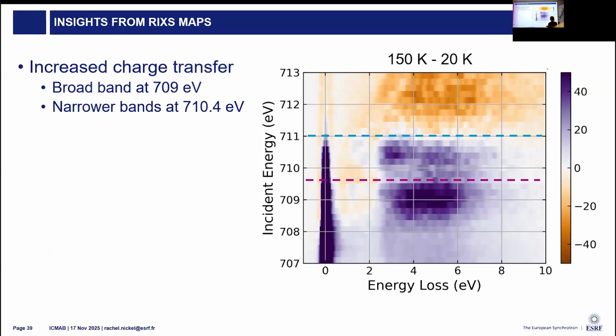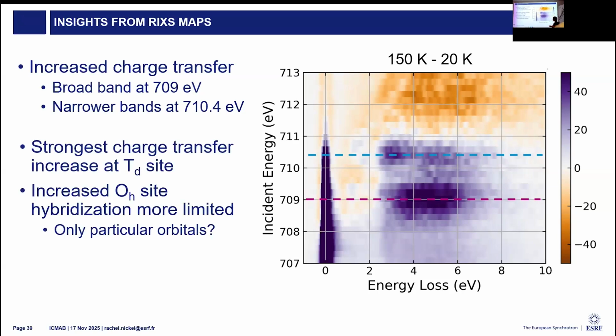So how do we connect it back to the RIXS map? It's an even shift of about 600 meV between where the DDs are resonant and where the charge transfer is most strongly changed. And so we can take these results and attribute it to stronger charge transfer, stronger hybridization of the tetrahedral site, as well as more discrete orbital overlap changes on the octahedral site. It seems that this is only affecting particular orbitals, and further information is going to have to be obtained using simulation. RIXS is still a little bit of a theoretical development in process, and so this is work to come